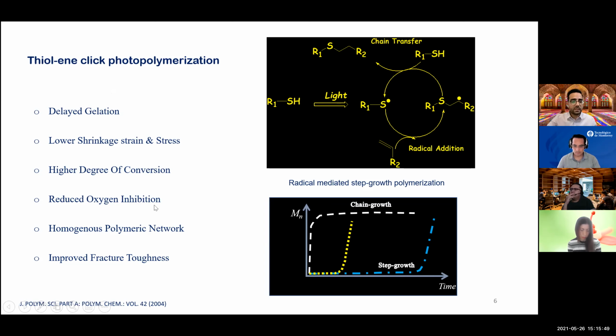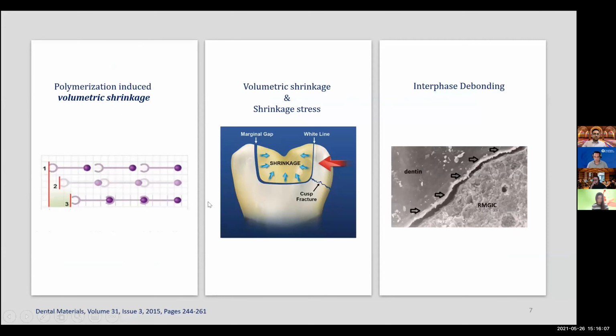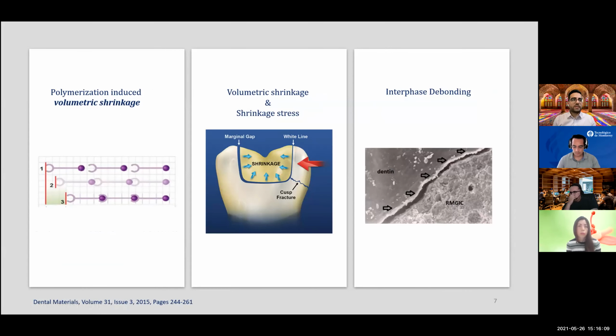And we know that in the conventional radical system, we have a bunch of problems in the presence of oxygen, and we have all the time a tacky surface because of incomplete polymerization. And we can have a more homogeneous structure, a more homogeneous network for those polymers, and improved fracture toughness. So the things that I want to mention are regarding my research project, and the